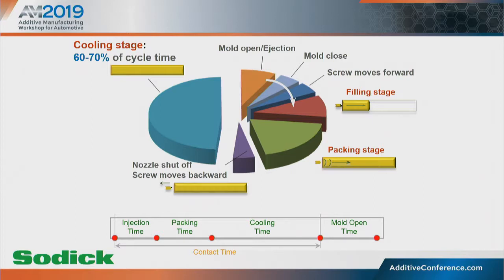So the reason that conformal cooling has been such a big topic comes down to what the actual cycle of a plastic part looks like. So when you look at the cycle of a plastic part, mold open time, mold close time, filling stage, packing stage, these all have relatively small times within that total molding cycle. Where you actually see the biggest time waste, if you will, is actually in the cooling stage, which at its worst can take up to 60 to 70% of the actual total cycle time of that plastic part. But this actually is an opportunity for improvement moving forward, because if you have this very disproportionate time scale for that cooling stage, it means any improvement that you can make to that cooling stage will also have a disproportionate effect on the total cycle time of that plastic part. So this creates a really great opportunity for reducing cost, improving efficiency of manufacture of those plastic parts.